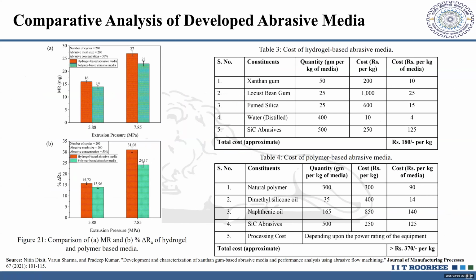Now, when we tried to compare this process with the conventionally used hydrogel polymer based media, you can see that the material removal rate is increased compared to this green colored line. The orange colored line is higher. At the same time, the percentage improvement in the surface finish is not that good, but it is comparable. So it is 15, 13, 31, 24 in nature. So no doubt, performance wise, I am able to get a higher material removal rate.